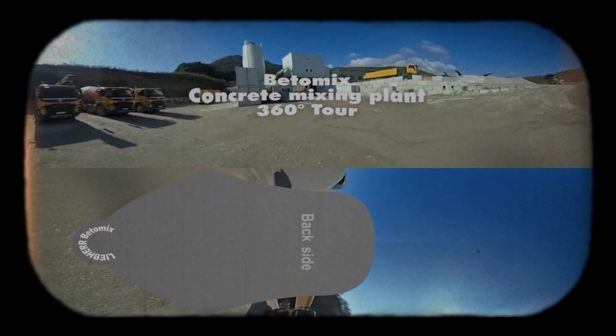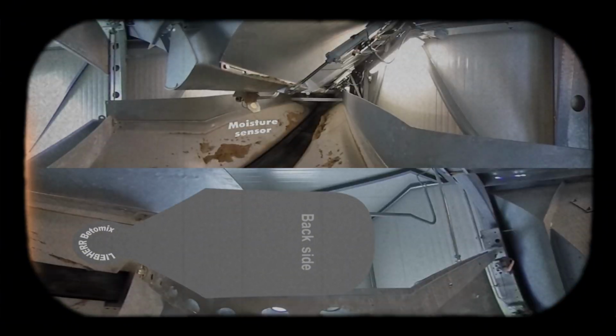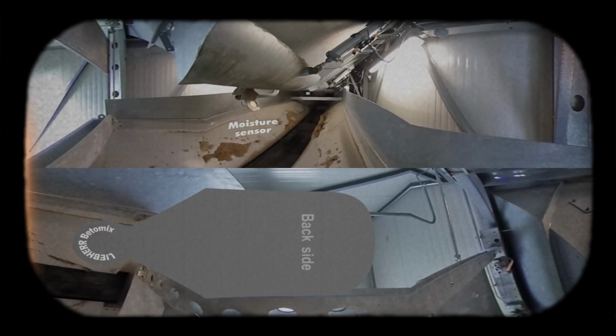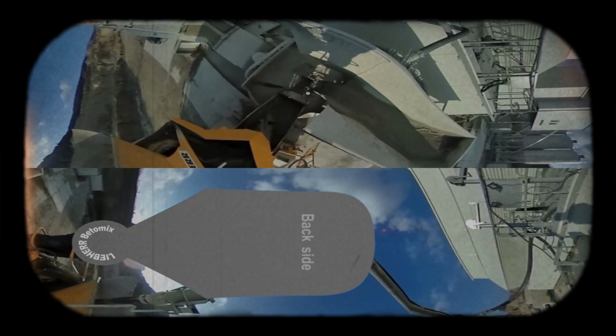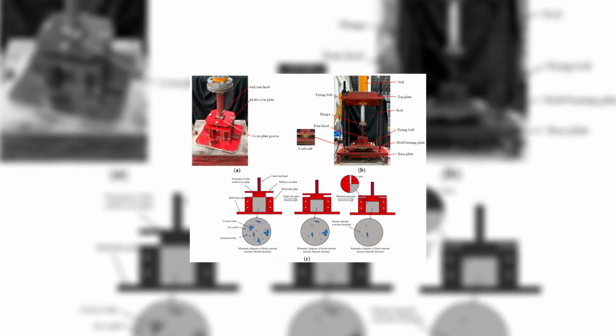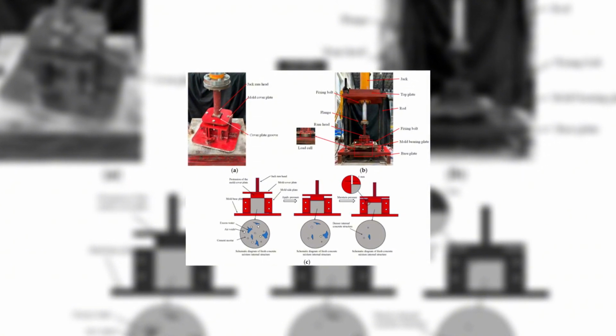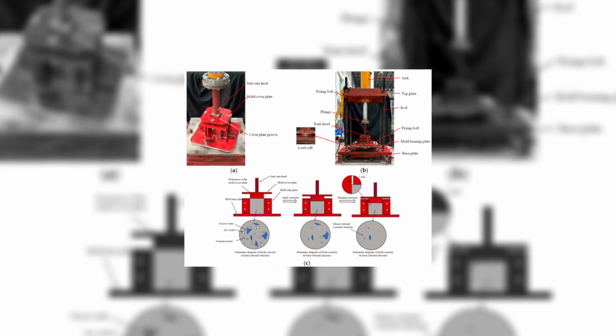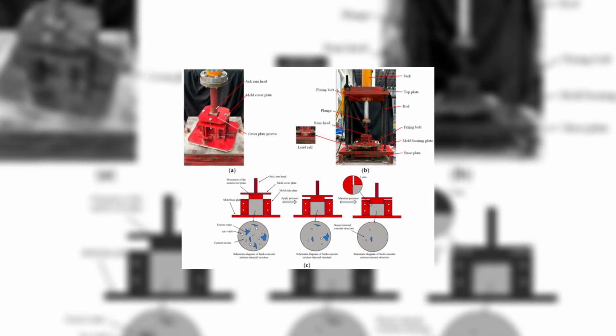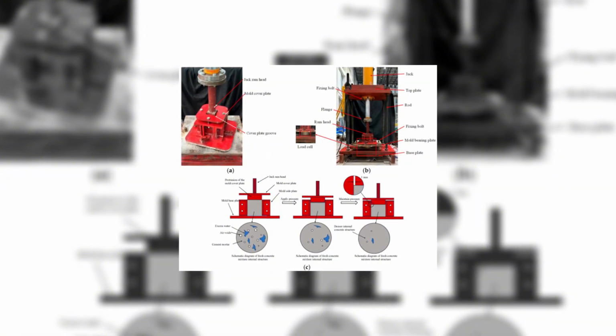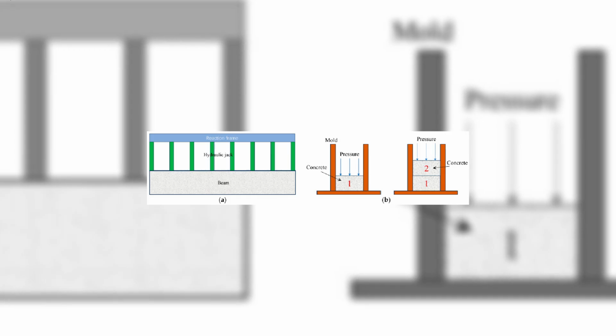The process begins like normal concrete production. The cement, aggregate, and water are mixed together and placed inside a specially reinforced mold. Then pressure is applied while the mixture is still fresh. In the research published so far, pressures above 5 megapascals have commonly been maintained for roughly 2 to 5 minutes. For perspective, this is not someone pushing down on a mold with a heavy weight. It requires industrial hydraulic equipment and molds strong enough to resist forces that would destroy ordinary formwork.